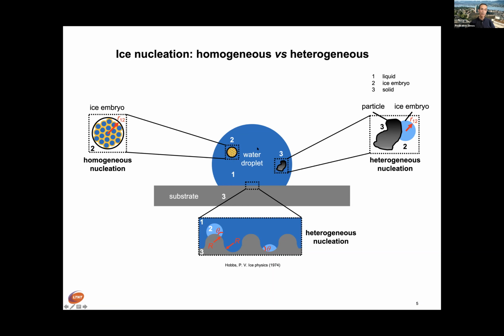And of course, they can form in the body of water, or if you have an impurity in the water, they will form on the impurity, and that is preferable, as we'll see in a while. But of course, the biggest impurity we have in application is a huge impurity. It is the surface upon which your liquid rests, right? So really the role of impurity in most applications is taken over by the surface. And as you'll see in the next slide, these surfaces tend to help and accelerate ice nucleation.